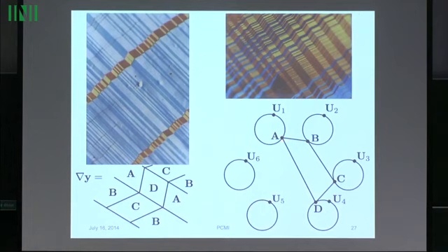It's not an usual situation. I mean, if I had, instead of going from this well to this well, I had tried to go to this well, it wouldn't have worked. Or if I had, instead of taking B, I had chosen the other rank 1 connection, it wouldn't have worked. So anyway, what those rank 1 connections mean is that A and B are compatible across this interface, and C and D are compatible across this interface. And in fact, those 2 interfaces coincide. So the rank 1 connections implied by those straight lines mean that all these interfaces are compatible.